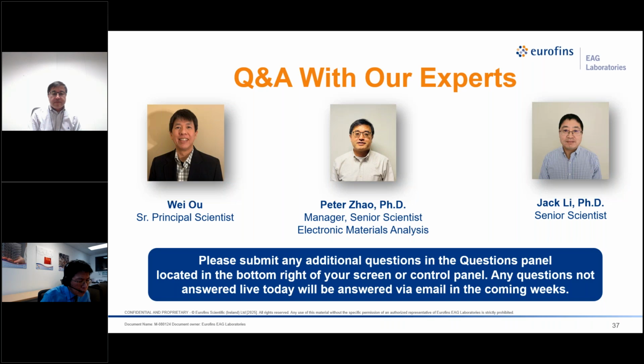How about silicon carbide power devices? What are the lateral dimensions you can go down to for the SIMS measurements you describe? We have different types of dynamic SIMS: we have Cameca SIMS, we have quadrupole SIMS, and we have ion TOF. The typical size for Cameca is around 200 micron, but we can analyze a small area as small as 20 micron. For the quadrupole, usually it's over 100 micron, and we can go to a smaller size, like 50 or smaller. For ion TOF, we can go to a couple of microns, like 2 or 3 micron.